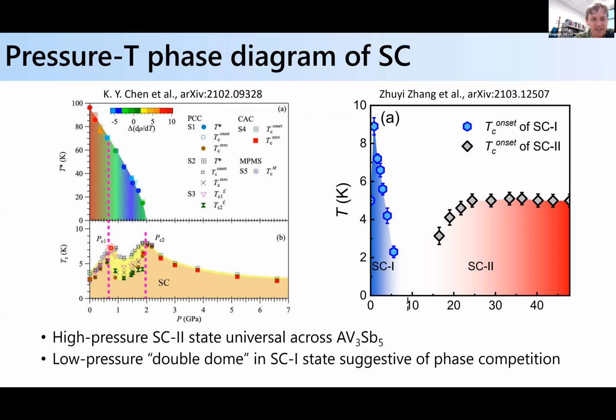They see superconductivity, the TC goes up in the cesium system, and then it starts to go down, and then it comes back up, and then it goes down again and flattens out in the low pressure regime. So in the low pressure regimes you have these two peaks in the dome, which is potentially suggestive of unconventional superconductivity or some unusual phase competition going on in this regime.